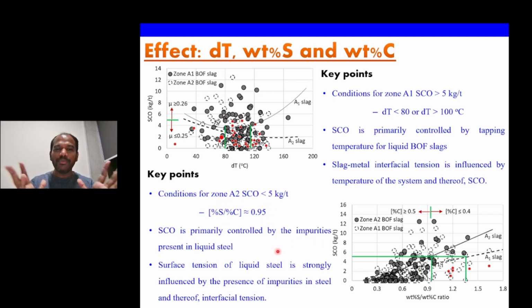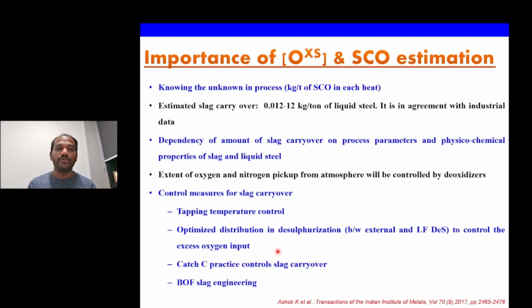Okay, so primarily the observation that comes out from here is that the interfacial tension involved can be controlled by several parameters. More importantly, temperature and the impurities present in the liquid steel have a major influence on the slag carryover. Importance of excess oxygen in the slag carryover estimation, I think I need not emphasize to this audience, because all of us must be very much aware of it. We want clean steel, and it has to be a slag free tapping.